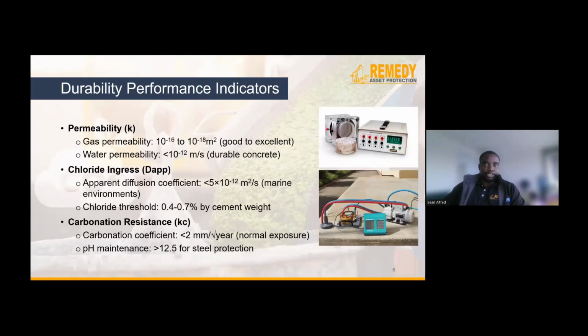In the world of concrete durability, there are performance tests, like I mentioned, the durability indicators, or what we call performance tests, that are employed to assess various characteristics of the concrete with respect to its resistance against deterioration mechanisms. And chief among these are chloride and carbonation-induced deterioration. Now, tests for permeability, chloride ingress, and carbonation resistance give an indication of the ease with which we can anticipate deleterious materials to penetrate the concrete, which then affects the deterioration, particularly of the reinforcement. And you can see here some respective values that I have added that would qualify as acceptable good durability performance indicators with respect to either permeability or diffusion or carbonation coefficients.